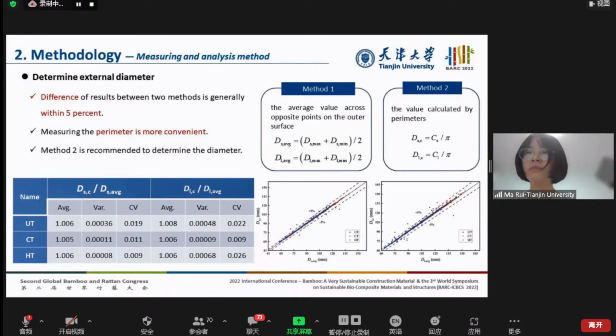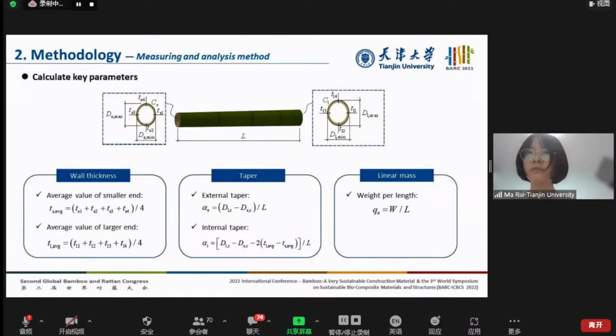The relation between the 2 methods is shown in the figure. It can be seen that the difference between them is generally within 5%. Meanwhile, measuring the perimeter is more convenient than measuring maximum and minimum diameters in practice. Therefore, the perimeter is recommended to determine the diameter of moso bamboo culm in this study. As average wall thickness of smaller and larger end, external taper, internal taper, and linear mass are calculated based on the following formulas.